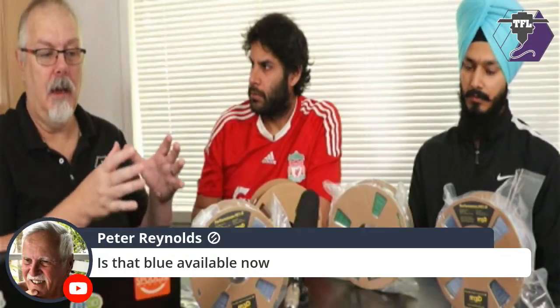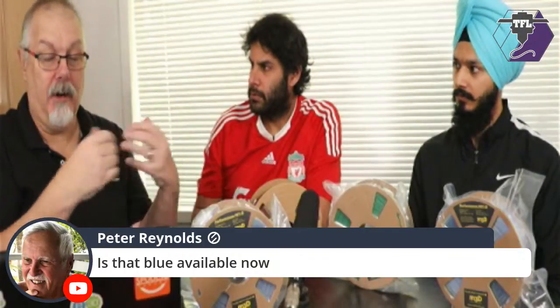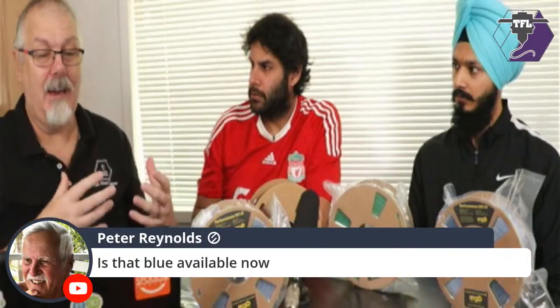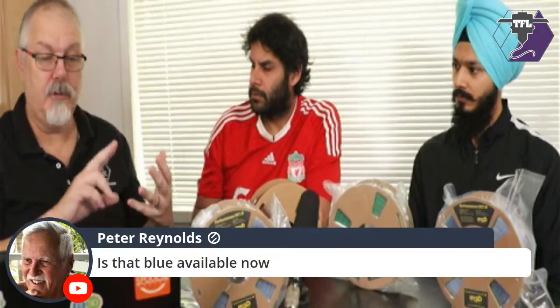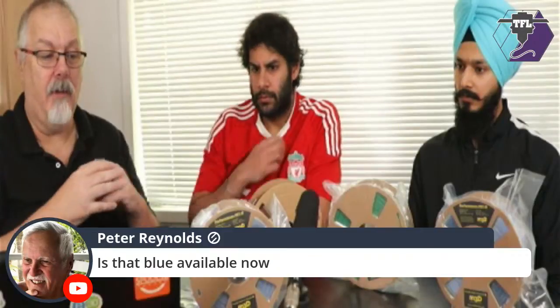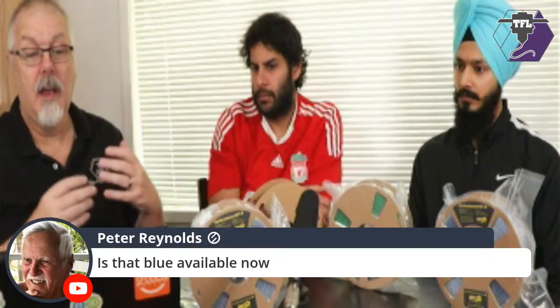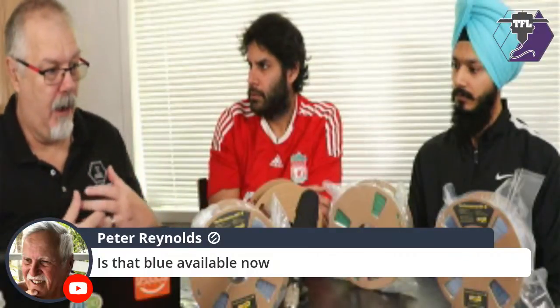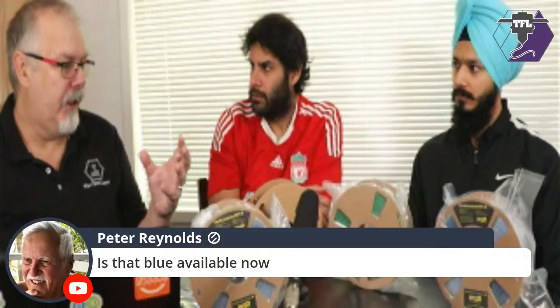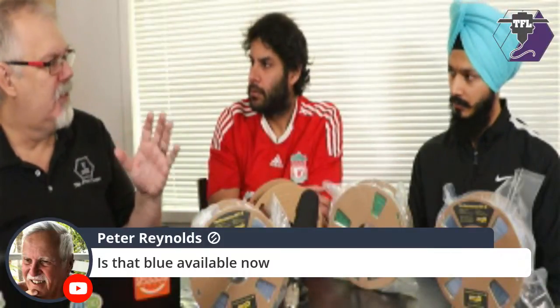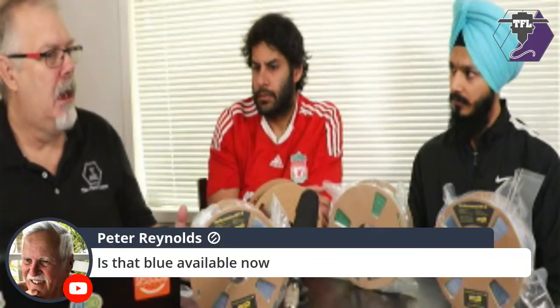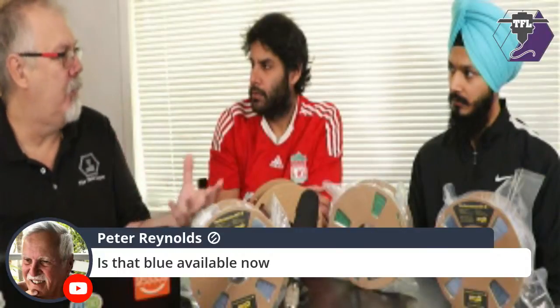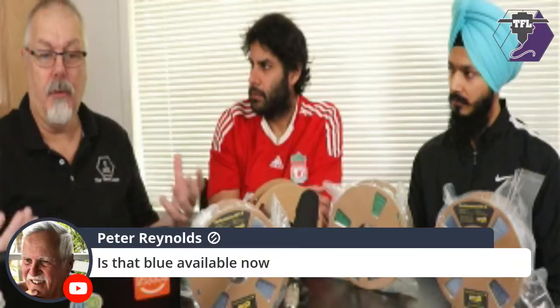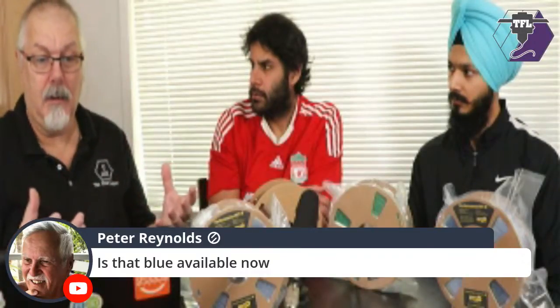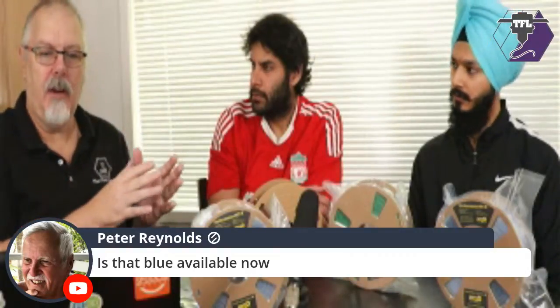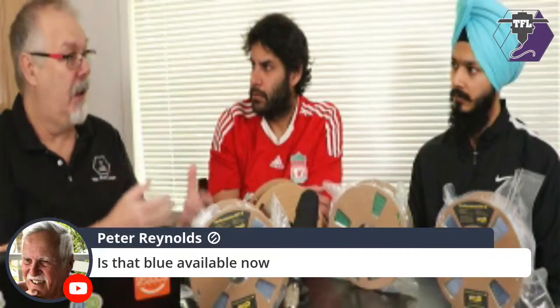But now you've got an actual material here, and from me using it for as long as I have, I can verify that this material will always give you consistent results, will always print great. And it's just a matter of how you dial in your machine and what printer temperatures you're using. And I found in my studio and my lab that we print this right around, like your PLA, right around 210, 215. Sometimes we go up to 220, depending on the color. White is one of those materials that has to be printed hotter. And for anybody that doesn't know, the reason that white has to be printed hotter is because it doesn't retain heat. So you have to print that hotter. And I've noticed that to be true not only with PLA, but also with ABS and with PETG.